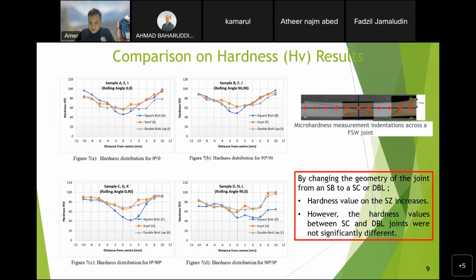As we can see, by changing the geometry of the joint from square butt to scarf joint or DBL, double butt lap joint, we can increase the hardness value in the stir zone. However, the hardness value between the scarf and double butt joint is not significantly different.